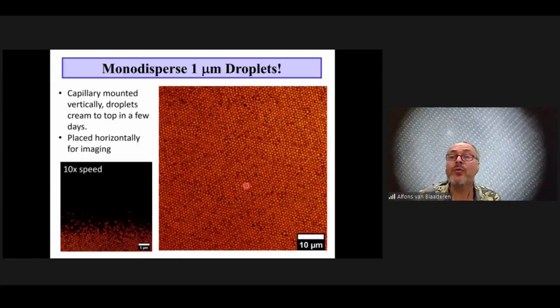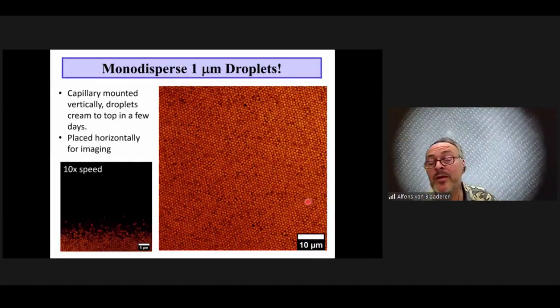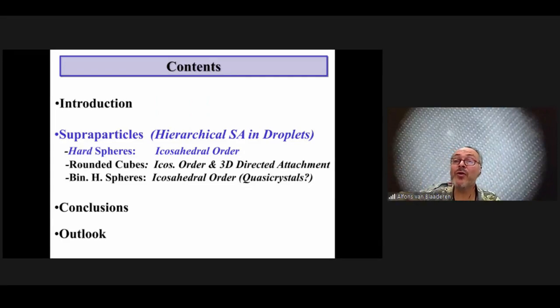What's also very exciting, but because of time, I'll only flash up this beautiful example of 1 micron droplets that we can now make with microfluidics with 5,000 nozzles in parallel at the same time. So we can create on the order of 1 gram of monodisperse droplets in 1 day of flowing, monodisperse enough that they crystallize, and on the order of a micron in diameter. That's very exciting, but I'm now going to focus on what happens in 1 single droplet.